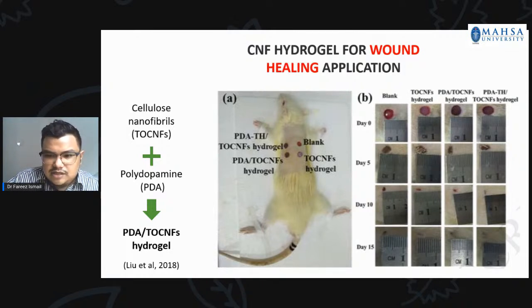And they introduced polydopamine, PDA, into this network and fabricated it into a hydrogel through using calcium ion as a crosslinker, and this hydrogel was used in both wound healing application as well as in drug delivery. And I'm focusing now on the wound healing application, as you can see in the result. The composite containing this polydopamine has shown a better recovery on the wound healing compared to other groups.